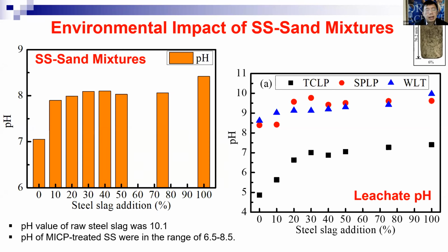So basically, in terms of the leaching pH, on the right-hand side of this figure you can see this, because the leaching pH can influence the leaching behavior of the metal. So we really need to know what the pH will be. When we look at the leaching pH in these figures, we can see the leaching pH basically increases with the steel slag percentage.